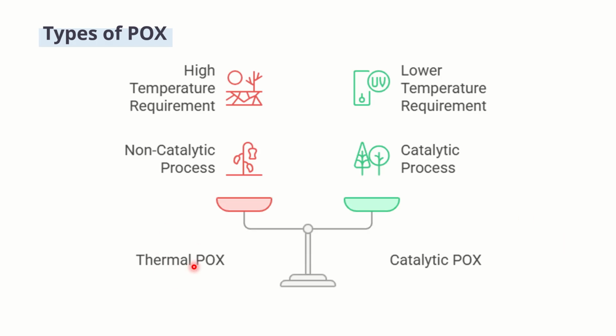The types of partial oxidation process are the thermal partial oxidation process and the catalytic partial oxidation process. Thermal partial oxidation process does not require any catalyst. It is a non-catalytic process, but it requires high temperature. Catalytic partial oxidation process, obviously, requires a catalyst, most often platinum on aluminum oxide, which operates at temperatures around 800 to 900 degrees Celsius. And this process is generally faster and requires small reactors, but they are sensitive to sulfur impurities.